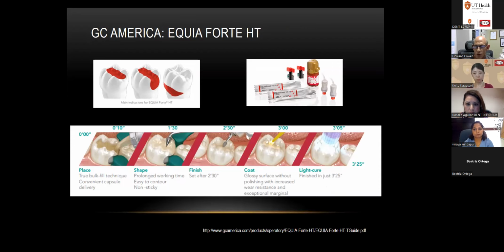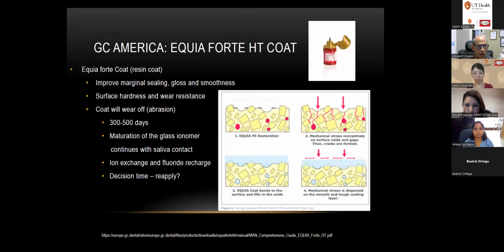if you want to light cure the coat afterwards, but it's a pretty quick procedure. It sets up nice, it's compactable, great material. If you haven't used it, you really need to start using it. Improved marginal seal with the smoothness. If you use the coat, the coat will wear off though, it's not meant to last, it's an unfilled resin, okay? It does prevent ion exchange and fluoride recharge on top, okay?